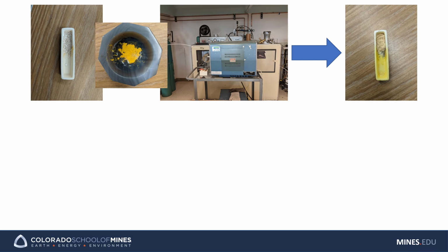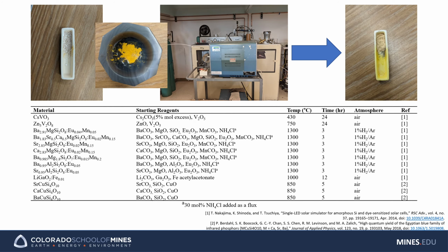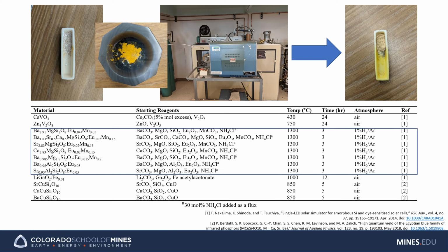So we made these nice little powders by just mixing them and crushing them in a crucible and doing a furnace treatment. These are our 13 secret spices that we use to make all the phosphors. And this very basic procedure of just throwing some powders into a furnace was working really well until we hit our highest temperature treatments. That's those 1300 degrees C treatments right there. And as soon as we started doing treatments at 1300 degrees C, we ran into some issues.